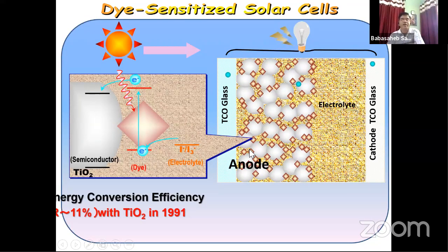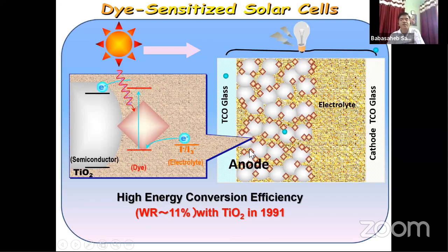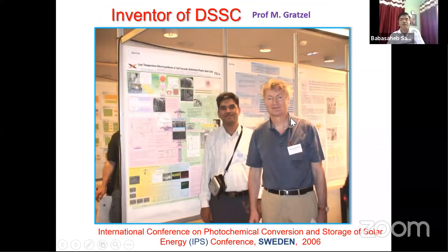The highest record efficiency was achieved in 1991, at 11% with TiO2, by Professor Michael Gratzel. And till today it has reached 12.5%. This means there is not much improvement in device efficiency because of some limitations of this solar cell. So instead of TiO2, we have thought to use zinc oxide, as zinc oxide has similar properties to TiO2. Professor Michael Gratzel worked on the dye-sensitized solar cell, and a lot of work has been done, and industries are also working and producing this type of solar cell, and these are available in the market as well.